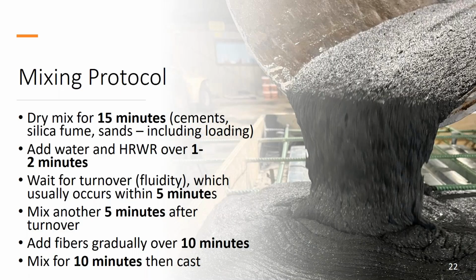And so in the lab, we typically mix for 5 to 7 minutes, but in the truck, we mix for longer. Then you add the water and high range water reducer, you mix them together and then add it in slowly. And then you wait for fluidity, we call it turnover, which happens about 5 minutes after the water is added. You wait another 5 minutes to make sure that it has turned over well, and then basically add the fibers.